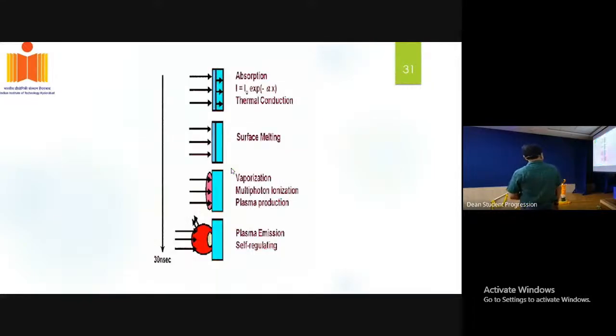So if you look at the entire process, from the moment the laser falls on the target material to the deposition, the entire process will happen in 30 nanoseconds. The moment the laser falls on the material, immediately it will go and deposit on top of the surface. So that's the power this pulse will have.